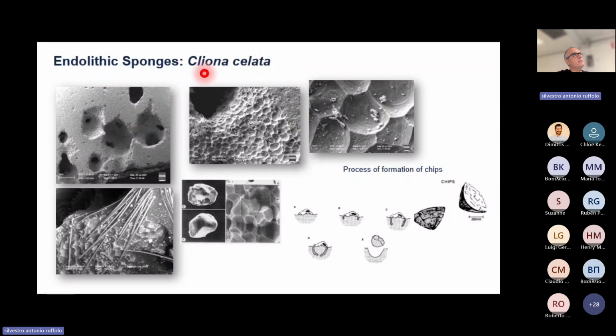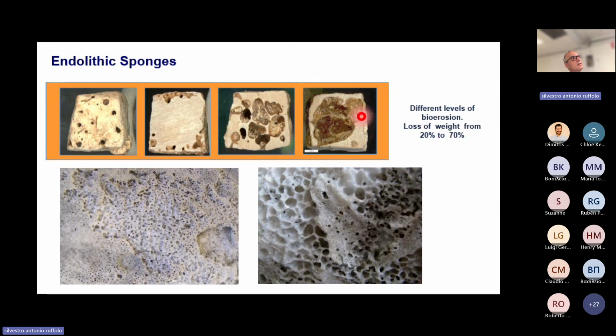Here there are some SEM images of how a carbonatic substrate can appear after endolithic attack. Here, the endolithic agent was Cliona celata. Here there are some spicules of Cliona celata, and these are the footprint, if you want to say, of the Cliona celata. It can make very severe damage. Here is a limestone with different levels of endolithic attack. As you can see, I can have very severe degradation, up to 70% loss of material.